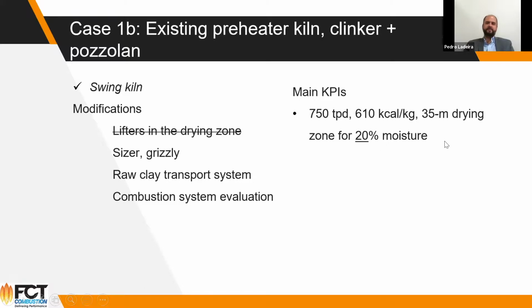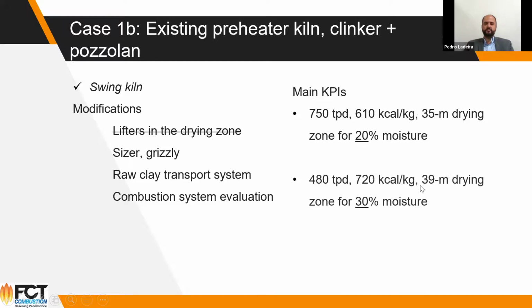But if this feedstock varies from 20% moisture up to 30% moisture, things can change drastically, and the kiln can lose production from 1,000 to 750 on pozzolan, and then 480. And a higher heat consumption, of course, you're drying more water. You have a longer drying section, and then you have to dry all the 30% moisture. So this one shows us how important is the drying section in the kilns.